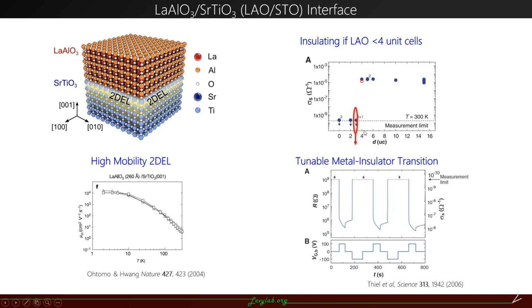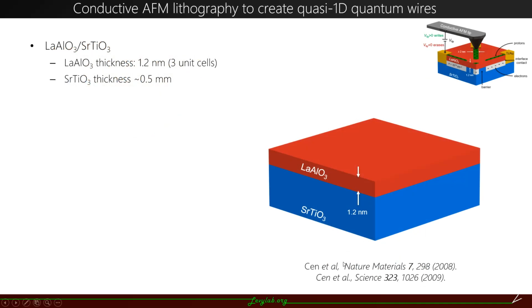However, if the LAO thickness is less than 4 unit cells, this interface could be tuned from insulating to conductive by applying a positive voltage and then tuned back to be insulating by applying a negative voltage. Using this fascinating property, our group has developed a system using conductive AFM lithography to write rewritable conductive nanowires at the interface.